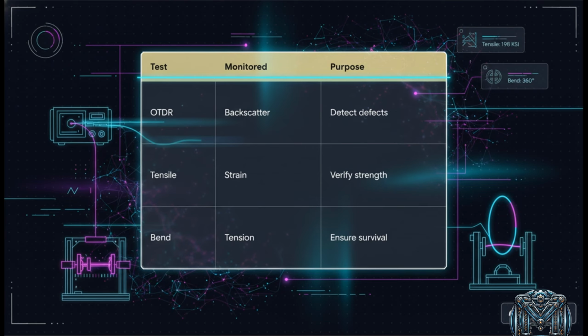We use an OTDR, that's an optical time domain reflectometer, shooting light pulses to hunt down microscopic backscatter from hidden defects. We subject the fiber to tensile testing of up to 200 kilopounds per square inch of strain, and we run it through intense 4-axis bend tests. We are literally simulating the physical torture of real-world installation to make sure it never fails out in the field.